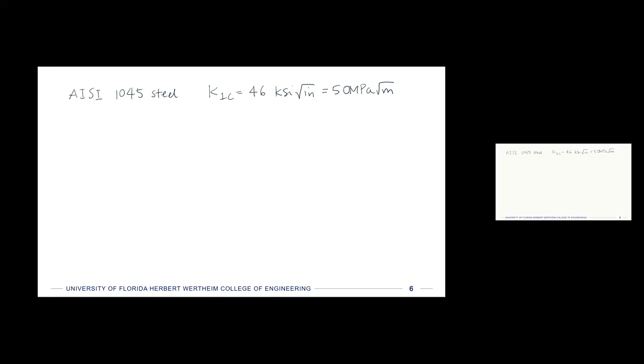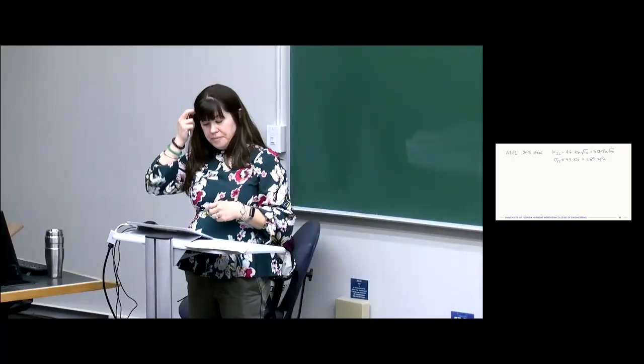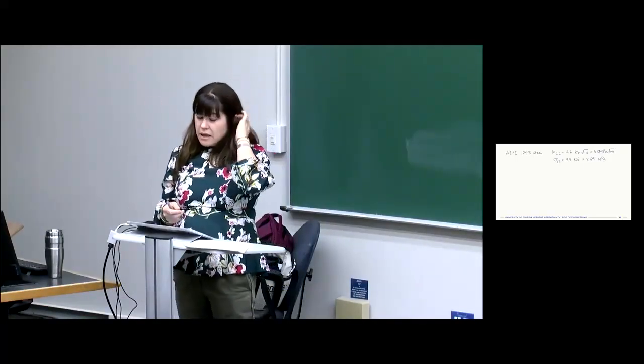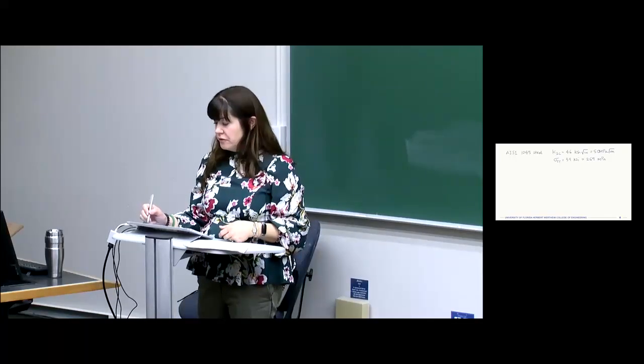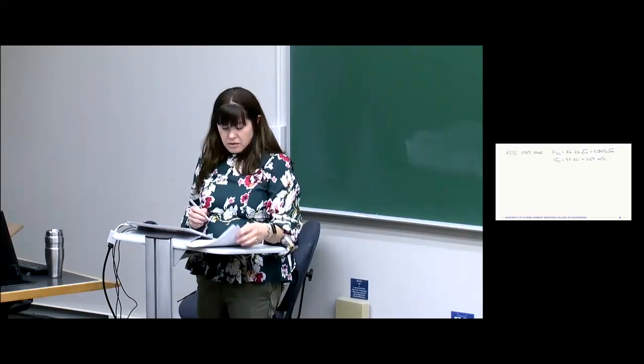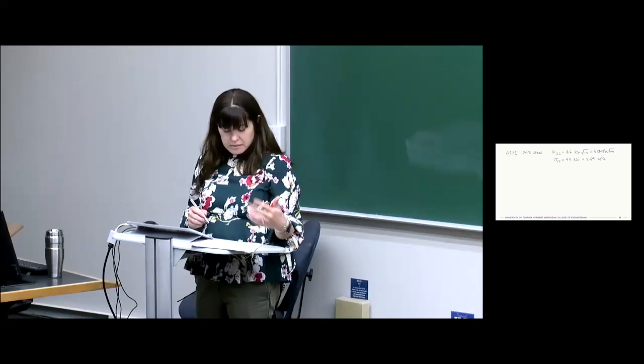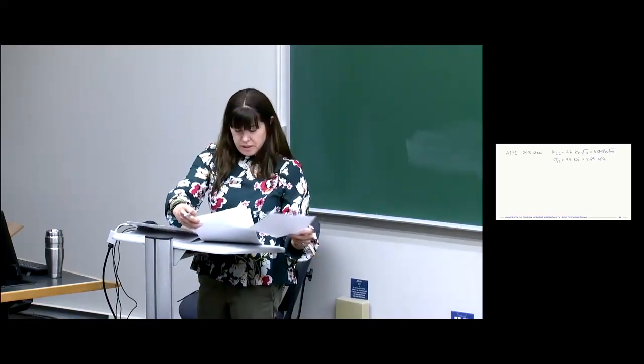And for reference, the yield point of this same material is 39 KSI, which is equal to like 269 megapascals. Okay. And so generally the orders of these things follow each other, but you can't predict one from the other, right? Because the yield point is a sort of a continuum property that was determined from a tensile test. And the K1C is also a property, but it includes the flaw length in that. And so it's more complex than that. So you cannot just infer one from the other.